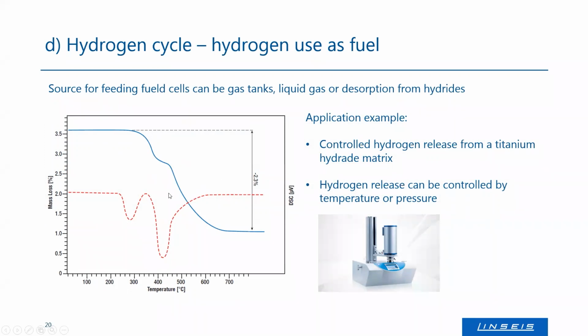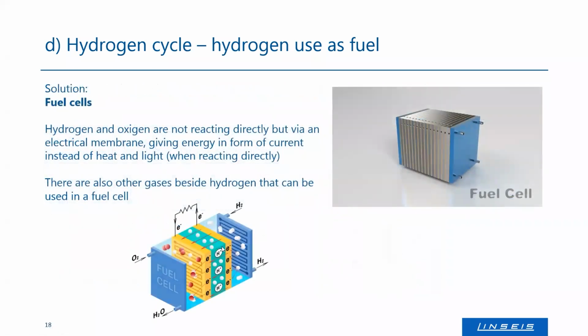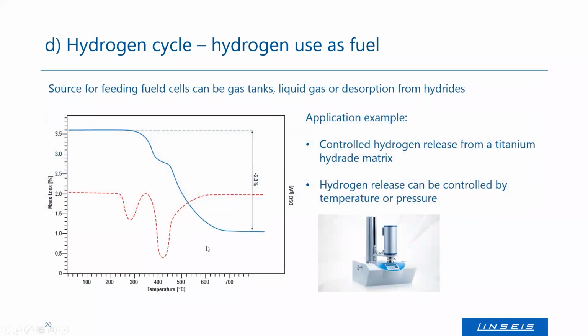And if you have a constant hydrogen release, then you have a constant possibility to feed something like a fuel cell. That was also measured by a thermal balance, as you see here. And that was the slide that I was missing 2 slides ago. I'm sorry for the mix up here. And once you have this controlled release, you can feed the fuel cell and anything like that.